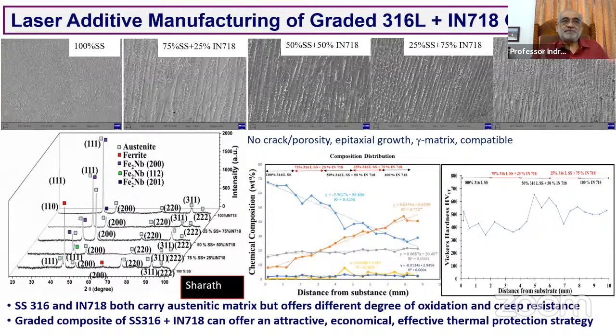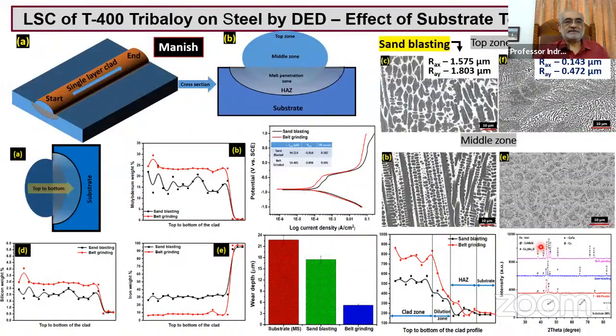Because of the temperature I'm using, stainless steel can very well withstand it, but stainless steel cannot withstand the oxidation at that temperature. So I make the surface with 718, and these are the diffraction analysis profiles, which show what the phase aggregates are. This is how the composition varies, and this is how the hardness and other properties change.